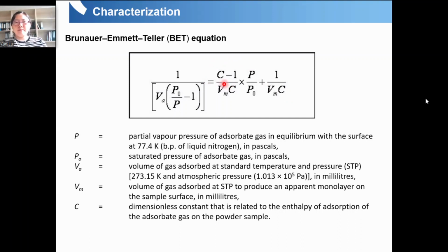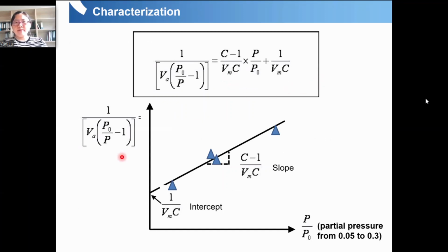And so for the BET, normally for the gas adsorption and desorption, what you have to do is measure P over P0, the partial pressure, and VA, which you measured. When you draw the curve, use this as the Y axis and this as the X axis, then you will get a linear relationship, so you fit your data with a line. With the slope of this line, you will get this, and with the intercept of the line, you will get this. Then, of course, you can calculate the constant C and the adsorbed volume of your gas.